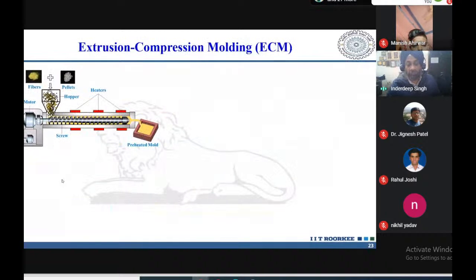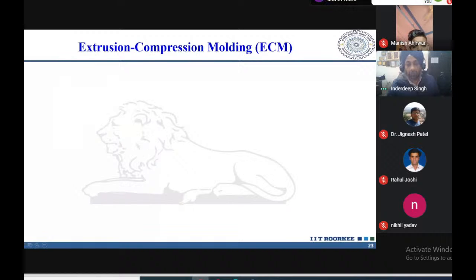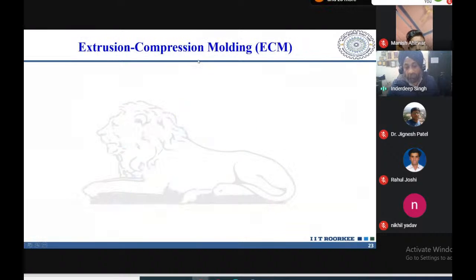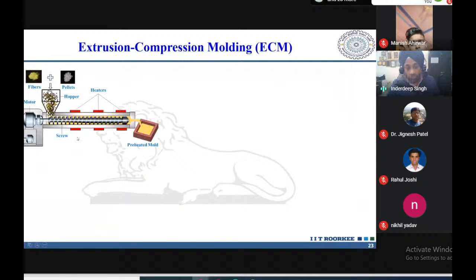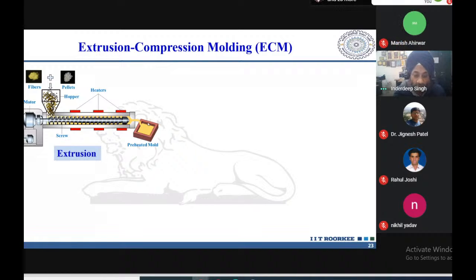Then instead of pelletizing here, if we change this process, after extrusion we collect this extrudate into a mold, then we can call the process the extrusion compression molding process. So here you can see, in extrusion we are trying to collect this extrudate in a preheated mold. This is the same process of extrusion, but here we are not pelletizing or cutting the composite strand or the extrudate into composite pellets, but we are collecting this in the preheated mold.